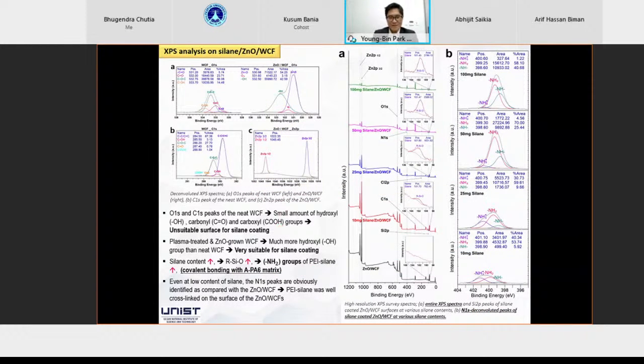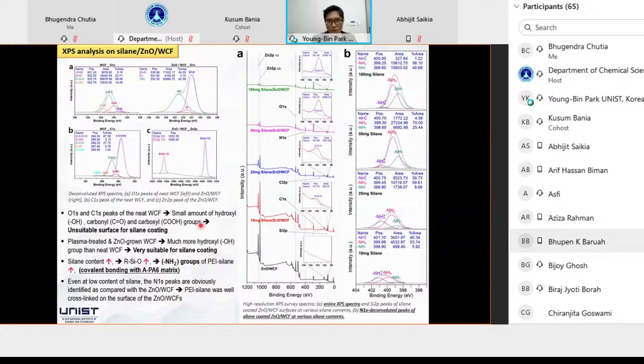Okay? And we also had to confirm that the silane was properly coated on the carbon fiber. Remember, this silane, which is a coupling agent, contains the carbon nanotubes. And we want to make sure that the silane is chemically interacting with the nanorods as well as the plasma-treated carbon fibers. And of course, the silane coupling agent naturally chemically interacts with the resin around it. Therefore, this is a four-way chemical interaction between the silane, the nanorods, the carbon fiber, and the resin. And in addition to that, we have reinforced the silane with carbon nanotubes. This is a five-way reinforcement scheme. So that's what we confirmed.